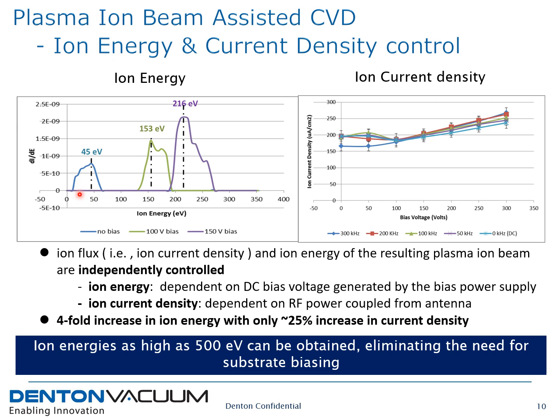There is a four-fold increase in the peak ion energy as the DC bias voltage increases from 0 up to 150 volts. On the other hand, there's only a 25% increase in the ion current density as the DC bias voltage increases from 0 up to 150 volts. In fact, ion energies as high as 500 electron volts can be obtained, although not shown here, eliminating the need for substrate biasing.